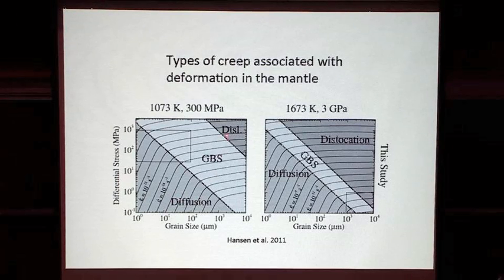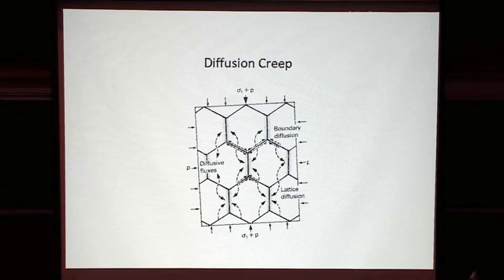So in diffusion creep, the grains are small enough so that you don't actually have to recrystallize the grains in order to accommodate change in shapes of the crystals because of an applied stress. But diffusion, either through the crystal or along the grain boundaries, is efficient enough to reshape the crystals in response to the deformation.